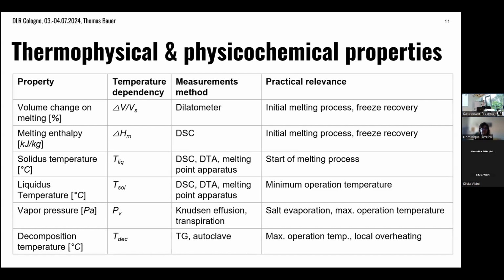And then we have the decomposition temperature, which typically refers to the thermal decomposition. So the maximum temperature of the salt can be limited by the thermal decomposition, by the corrosion, or by the vapor pressure. Typically, people also mix up what is the maximum temperature, what is the decomposition temperature, and so on. But we need to look at what is really the limiting factor of the maximum temperature.